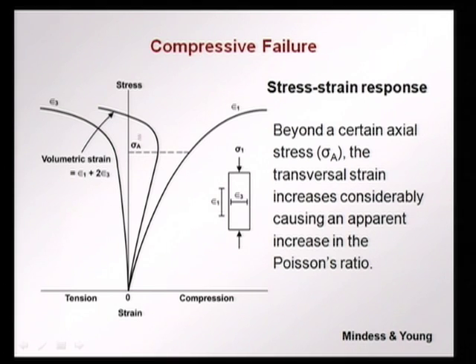Beyond a certain point, sigma sub a, which is limiting axial stress, the lateral strain increases very rapidly. This is because cracks develop, and these cracks now mostly are oriented along the direction of loading. So, they open in the transverse direction. So, the strain in this direction increases very much after the stress where the cracks develop. So, this means that volumetric strain, which is